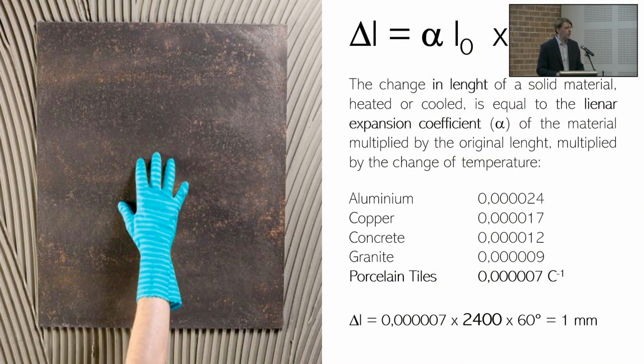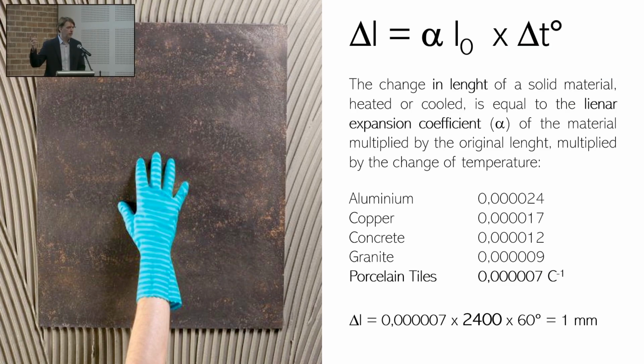Because the deformation of the tile, especially the grès tile, porcelain tile, let me say, is one of the most affecting problems when we are choosing the adhesive to do the job on the job site. Because if I consider the coefficient of deformation of grès tile, I will see that its proper deformation is very, very small. So if I ask myself, is this grès tile deformable or not deformable? The answer should be basically not deformable, because the coefficient of deformation of porcelain tile, you see there, compared to others, is very, very little.